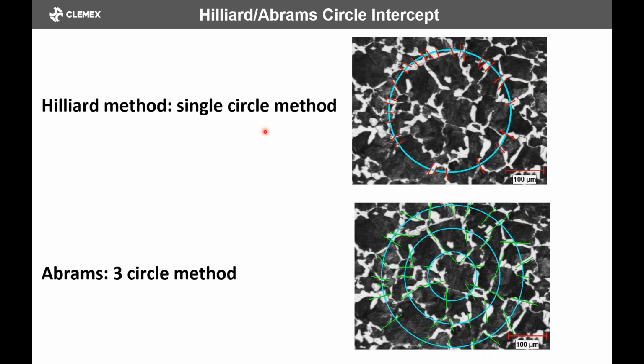One of the methods uses a circle, so it's an alternative to the planimetric method that we saw earlier. This is to continue with the intercept. So the Hilliard method was originally developed by having a circle of a certain size, and then you basically count the intercepts. Before it was on a ground glass or a monitor, but now you can do that directly on the screen, where you would count the intercepts, and then at the end you would measure the segment, right? The segment and the number of intercepts, and you have your method.